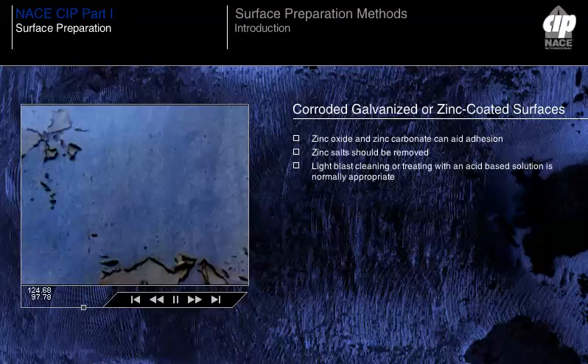Oil-based coatings, such as alkyds or epoxy esters, perform poorly when applied over galvanized or zinc-coated surfaces because of a reaction between the coating and the zinc surface called saponification. This reaction, the formation of soap, causes degradation of the oil-based binder and consequent loss of adhesion of the coating to the zinc surface.